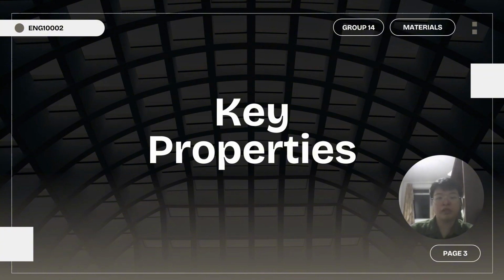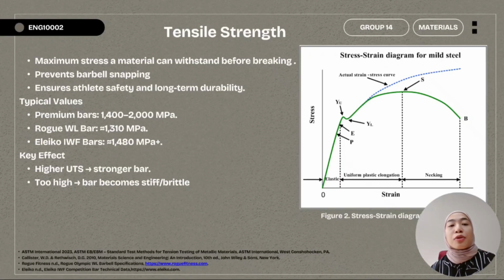Moving on, we'll talk about the key properties. The first key property will be tensile strength. Tensile strength is the maximum stress a material can withstand before it breaks. This is extremely important for Olympic barbells because athletes perform explosive lifts with very heavy weight. Most premium Olympic bars are designed to have tensile strength values between 1,400 to 2,000 megapascal. For example, Rogue Olympic barbell is around 1,310 megapascal, and Eleiko's IWF certified bar reaches 1,480 megapascal or more.